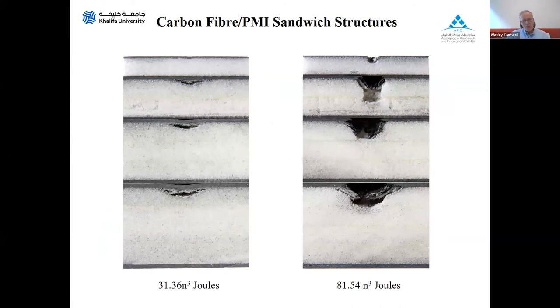Once again, when we section these samples, we look at the damage in the four scale sizes. This is N equals a quarter, half, three quarters, and N equals one, at two different energies. If we look at the lower energy first, let's start with the largest sample here. You can see that impact has created failure within the core, but very close to the top surface skin, where the local stress field has just caused some crushing of the core. And as the skin recovers, this fails probably in tension there. But we see a similar failure mechanism in the smaller samples. And even if one looks very closely, one convinces oneself that there is some sort of blemish there as well, even in the N equals quarter sample.